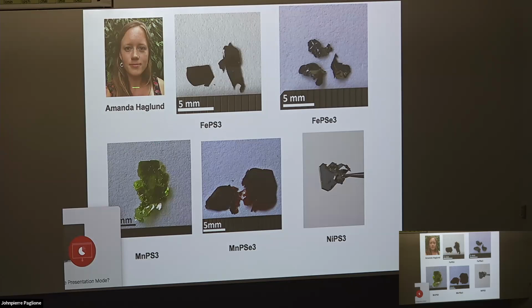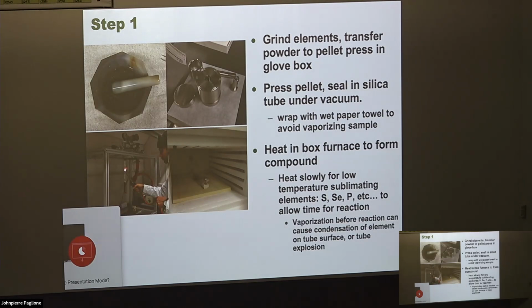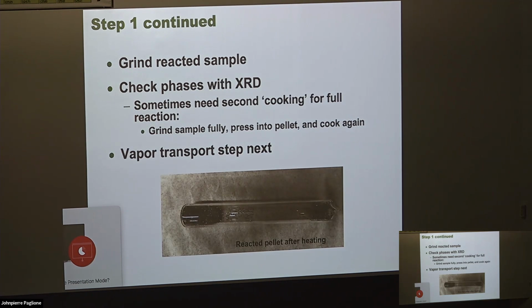The student who spent the most amount of time growing these things was Amanda. She's the one who put together most of these slides for us. Essentially, some of the tricks: you want to grind everything together, make it into a pellet, and press the pellet. You want to put it into a silica tube, but you want to keep the bottom of the tube cool if you can. You can put it into ice water. I think she would wrap it and put a wet paper towel around it. You could put it in liquid nitrogen if you really wanted to. So you want to form your starting compound. Then you can grind the sample. Make sure you have single phase.